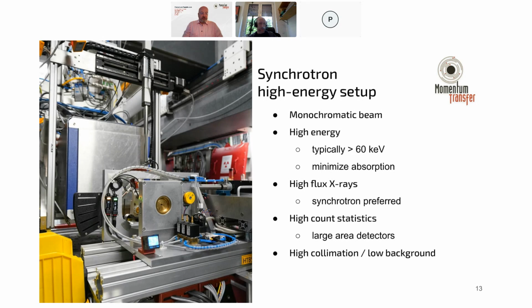And we also use large area detectors so that we can collect a wider spread of the X-ray diffraction signal, rather than using point detectors or position-sensitive detectors that typically only collect a very small part of the diffracted signal. And finally, we use a lot of instrumentation in this beamline to collimate the beam and reduce the background, to get rid of any artifacts from instrumentation upstream, and also to decrease air scattering. In addition to that, we also measure the experimental background and subtract it from the system.